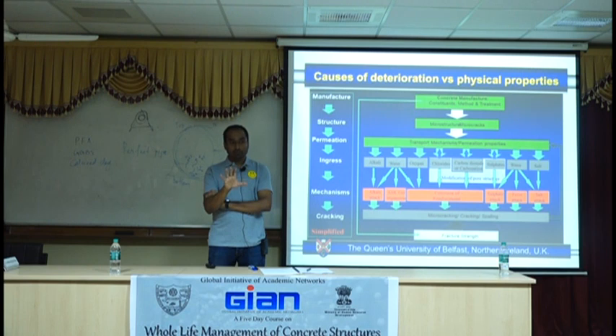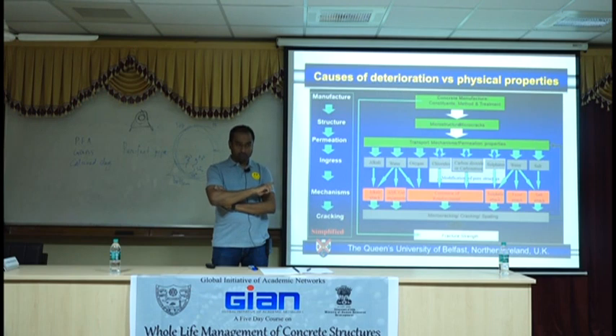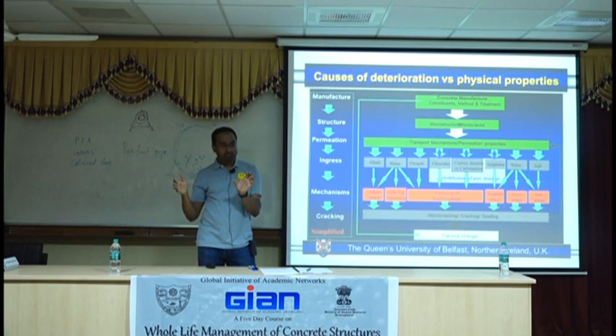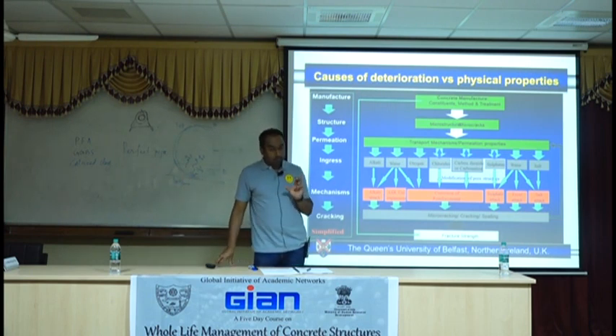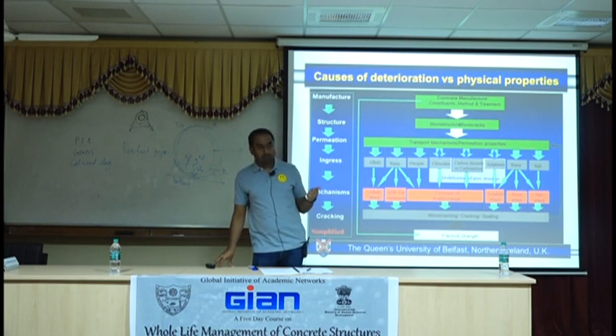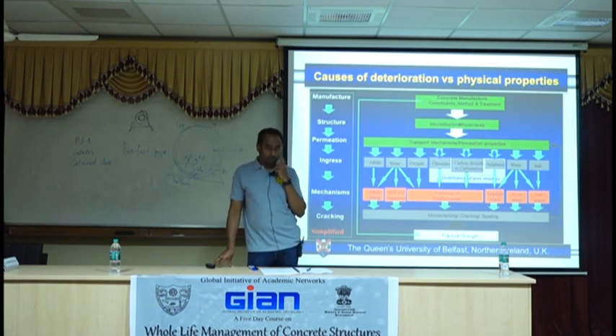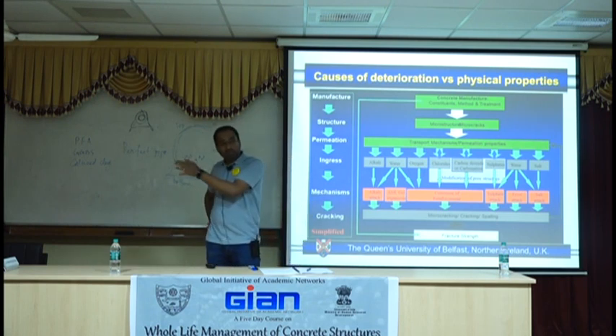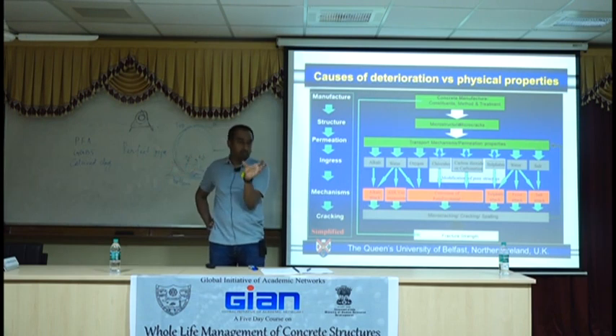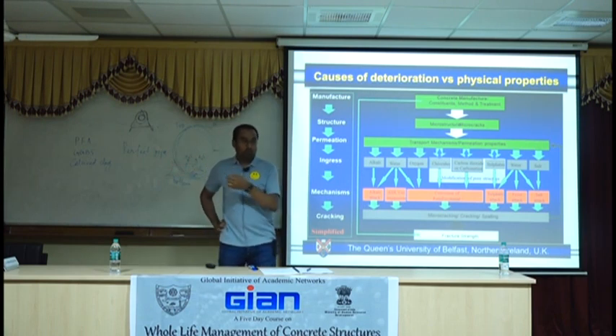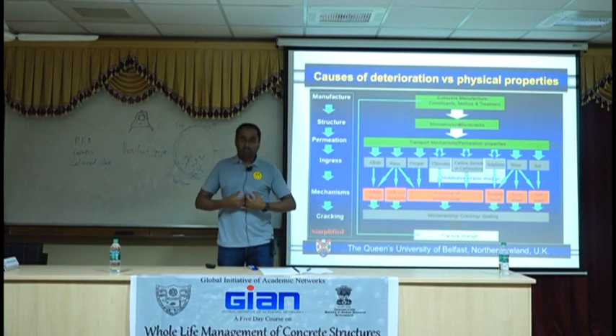When you're using high performance concrete, you can expect problems due to capillary suction. Okay. Corrosion may not be a possibility because it might be broken, and if you have decent cover, it's not going to happen. But other problems can arise. First of it is if it transfers salt and if the salt evaporates, efflorescence it's called. Then the water brings the salt in, a couple of millimeters, it's broken capillary, it deposits there, but water can escape, the salt can't. So it might actually have a cracking potential.